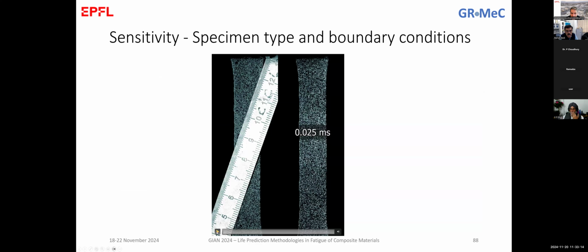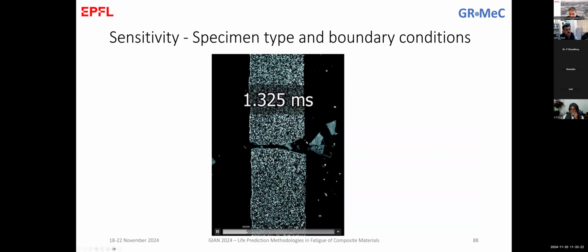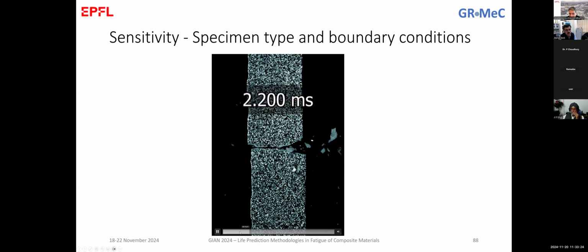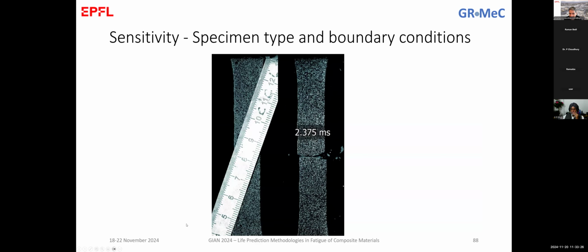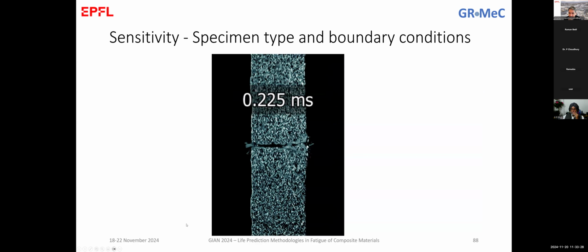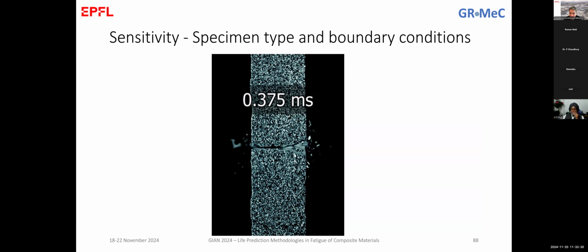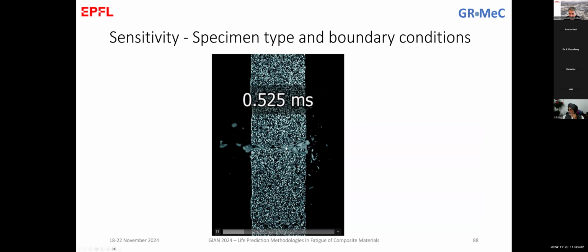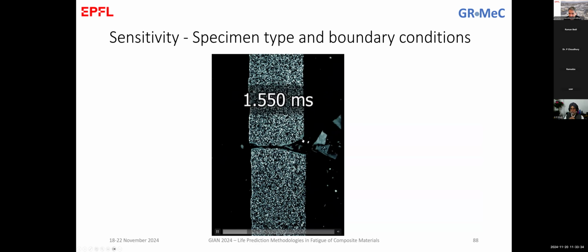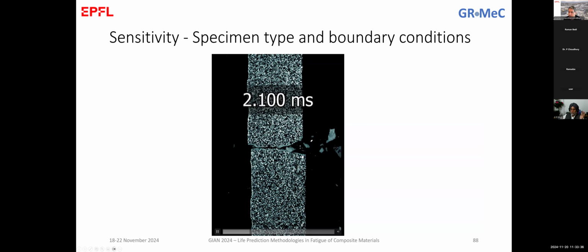So this is a high-speed camera measurement. You see the specimen on the right hand here. There is always this small piece that comes out. You see, probably I can let it run. This is a failure of the specimen, and what you see here on the right hand is exactly this effect of the misalignment.